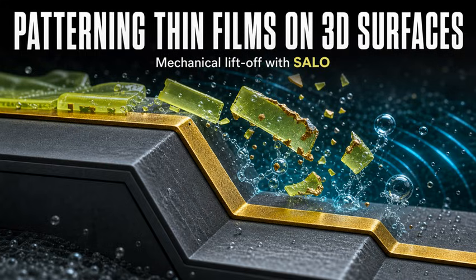Okay, so shrinking the mask gets us down to 27 nanometers. But does this actually hold up when we try to build those dream applications we opened with? It really does. They proved these concepts in the lab. They successfully patterned functional gold nanowires spanning 54.7 degree silicon slopes. Oh, wow. Yeah, and they also fabricated 1.5 micron line-width wire grid gratings directly on the curved tips of optical fibers. No way. And those gratings successfully diffracted 1550 nanometer infrared light. That is incredible. So if you can now use 2PP to pattern materials using ALD or physical vapor deposition, PVD, onto any arbitrary 3D topography, well, what previously impossible 3D electronic or photonic device will you design tomorrow?